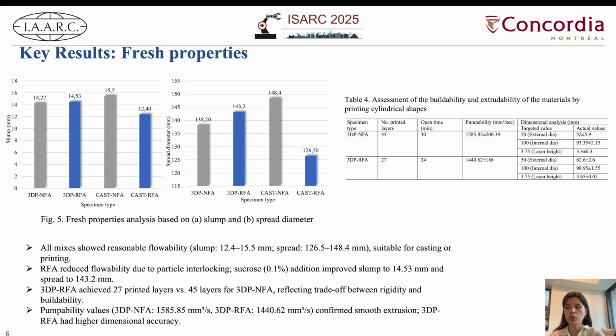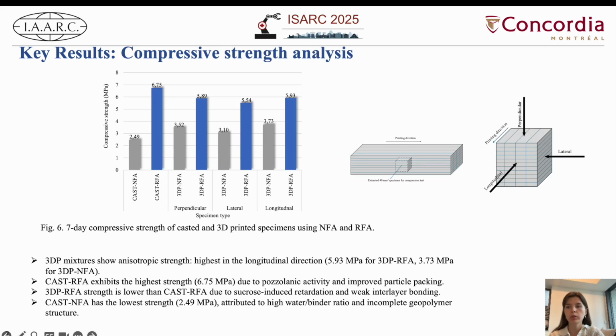Recycled mixture showed better dimensional control, which was confirmed through real-time printing trials. Overall, all mixtures with recycled fine aggregates showed better stability and dimensional accuracy, which are key for successful 3D printing. We evaluated the 7-day compressive strength.